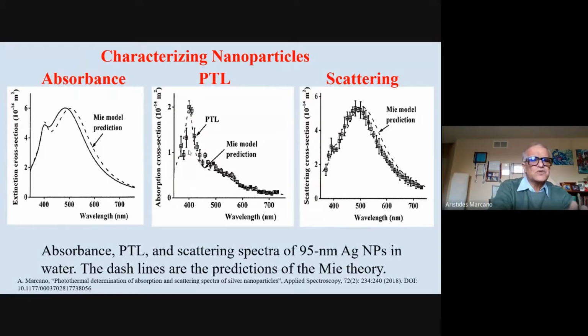And of course, if you subtract the two spectra, you get the scattering of the nanoparticle, and I compare it with the prediction of the Mie theory. The Mie theory also predicts scattering, and I see excellent coincidence. The paper was published about 5 years ago, after I went to Trieste, and I think I published that paper anyway.